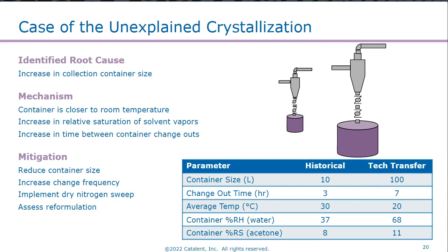Historically, on the smaller scale dryer, we had been using 10-liter collection containers and changing them out every 3 hours. At the larger scale, we were using 100-liter collection containers and changing them out every 7 hours. This change in size and then separation from the process by double flap valves led to a change in temperature in the collection container. This change in temperature actually leads to an increase in the relative saturation of those solvent vapors, being the water and the acetone, which is known to plasticize the spray-dried dispersion.